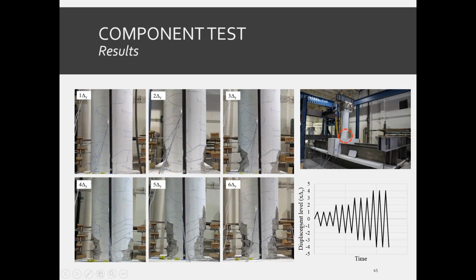The loading procedure is shown here. At each displacement level, 3 cycles were applied. The displacement level was increased by 1 delta Y after each 3 cycles, and delta Y is the yield displacement of the column calculated during the first cycle. We observed that the crack initiated in the plastic hinge region, which was followed by cover crushing during the first 3 cycles, and the cover spalling extended to large areas as the displacement level increased.